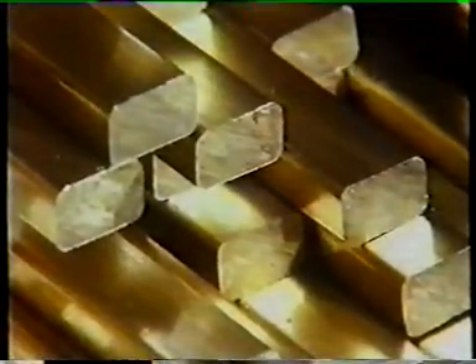The hot working properties of alpha-beta brass come from the structure of the metal, magnified here 100 times. Because the alpha-beta brasses contain more than 37% zinc, this appears as dark beta granules within the alpha structure. This makes the metal relatively brittle, and it needs to be heated before working.